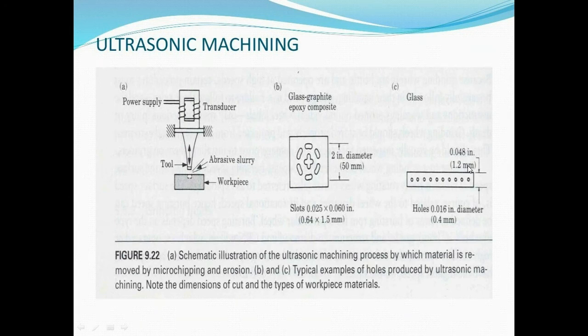Then the disadvantages of ultrasonic machining. The first one is that material removal rate is slow. Tool cost is high. The third one is high power consumption. The fourth one is that the size of cavity that can be machined is limited. Another disadvantage is that initial equipment cost is very high. Softer materials are difficult to machine. Then the limitations: penetration rate is 5 cubic mm per minute, power 500 to 1000 watt, hole tolerance is 25 micrometer, and surface finish is 0.2 to 0.5 micrometer.